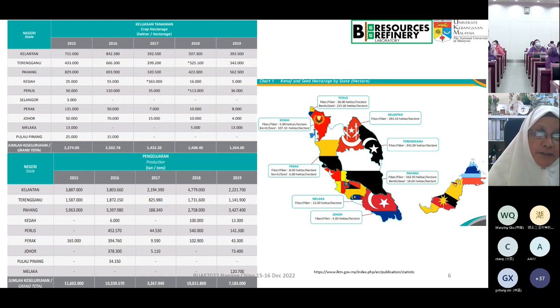And Kenaf has been introduced in Malaysia for more than 10 years, where many states in Malaysia started planting Kenaf. The northern part of Malaysia has been focusing on the production of seed as far as Kenaf is concerned. And they are trying to increase the area for Kenaf plantation because the demand for the bast fiber is higher. But the core part is not being utilized; about 60% of the Kenaf core is not being utilized because of the short fiber. So that is the reason why we thought it is a good idea to convert this Kenaf core into high value added products.